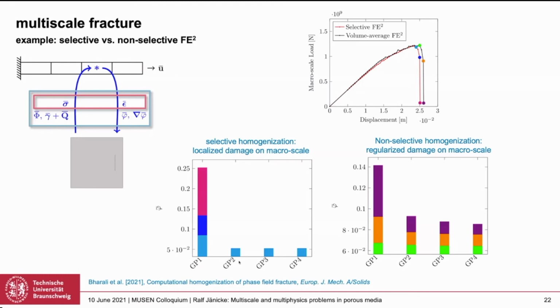So basically we have here a bar. Again, I would call it 1.5 dimensional, because there's only one loading direction on the large scale, whilst the subscale is two-dimensional. And here we only have a few elements where one element is a bit smaller in diameter, so that we have something like a notch there. So we can define where the crack has a chance to localize, because that's needed anyways.